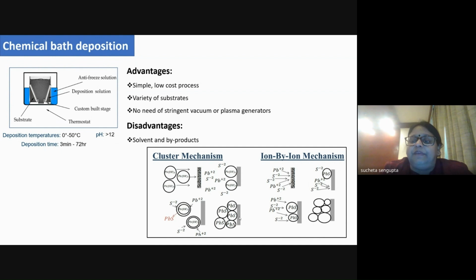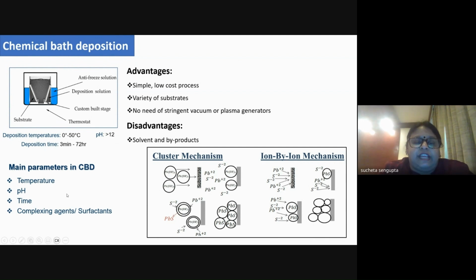In the ion by ion mechanism, however, you have the substrate upon which the lead or sulfide ions are being attached, and the PbS grows on the substrate itself. Obviously, the ion by ion mechanism helps to achieve better crystalline growth, and usually occurs at higher temperature. In chemical bath deposition, the main parameters that we tend to vary are the temperature, the pH of the depositing solution, the time, and also we can add a complexing agent, which complexes the metal ions preferentially and hence controls the release rate of these metal ions.